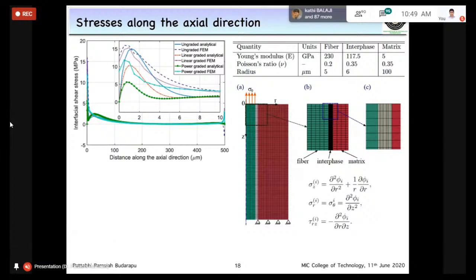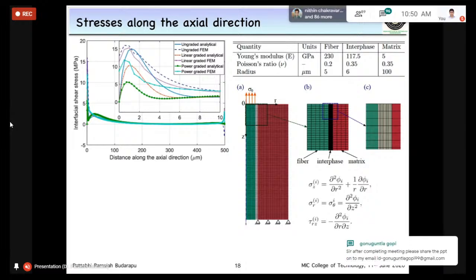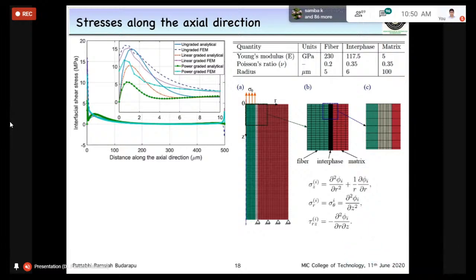Analytical models are perfect, so you can see from ungraded, the blue line, to linearly graded, the peak stress drops from 15 megapascals to 10 megapascals. That's the importance of grading. Whereas if I go for power grading, the stresses further drop to almost 5 megapascals, dropping by one-half, which is quite significant. This drop in peak stresses decides the load carrying capacity of the composite system, and this interfacial shear stress is the very key component.